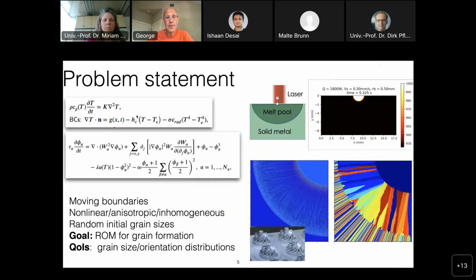And this is a more specific, simpler problem statement, in which we're going to see just the case in which we have a laser that shines in this position. It melts a semi-spherical region, and then this liquid metal solidifies. You can see here there's a laser. This is the temperature. You can think the white region here is liquid metal. This is solid, and then we're going to turn the laser slowly off, and then there will be the cooling and the microstructure formation. And this is the very simple setup.